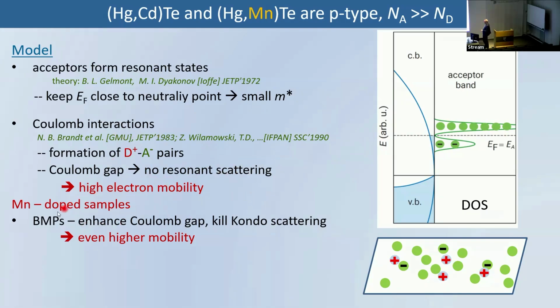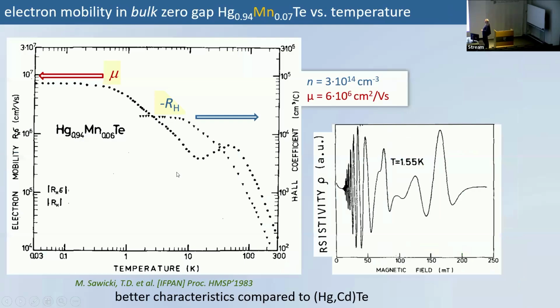In addition, if you have a manganese-doped sample, you have a magnetic polaron which forms and opens this gap even further. Experimentally, it was found indeed that this mobility is very large: 6 million in this sample. We went up to 22 million under pressure, and for years it was the highest observed mobility in any material. And this is not an error of measurement, because if you measure quantum oscillations, you also see that they start at very, very low magnetic field, about 20 millitesla, which means that mobility must be very high.